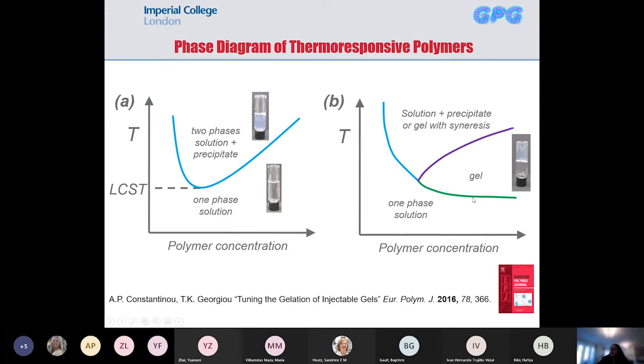And then as you increase the temperature and the concentration, you have the formation of a gel. And if you go even higher, you have the gel destabilizing. So normally you will either have polymer precipitation, or you may see visually formation of two phases. One can be a gel and then liquid as well. So that's called syneresis. So this is the area we are interested.